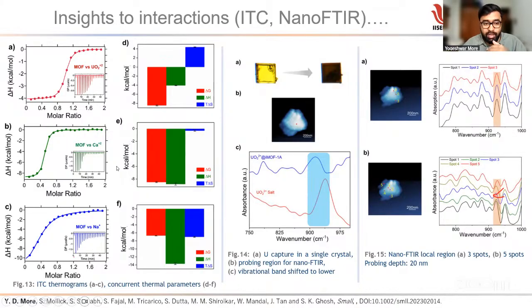Now, the extremely competitive ions in seawater with uranium, the very facile competition, are calcium and sodium, because they are present in very high amounts in seawater. Hence we chose these two candidates because they are going to interfere with the uranium. So then we did the kinetic as well as the rate study with calcium using ITC, and it was found that delta G is negative, but T delta S is also negative, and a negative T delta S means the entropy is decreasing, and that is not a favorable change.